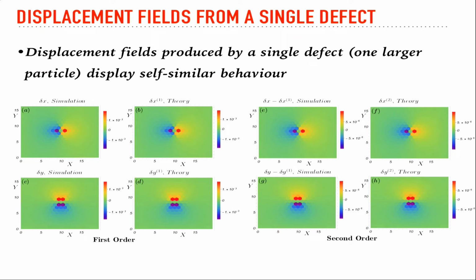So linear elasticity theory obeys the superposition principle. If I act with some perturbation on the system and I act with another perturbation on the system, linear elasticity would predict that whatever solutions of displacement fields you get would be superposable. But in a system of this nature, clearly you are not going to obey superposition. So if you want to understand corrections to linear elasticity, you will have to understand corrections at nonlinear order. So this is a mathematically exact framework with which you can do that. And so I'll show you some results that we have from there.